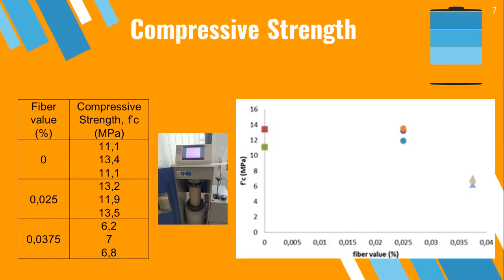For the compressive strength and tensile strength, both also decrease after adding fibers. Looking at the graph of compressive strength, at fiber value 0% we get an average compressive strength of maybe 12 MPa. At fiber value 0.025%, we get an average of maybe 12, similar to the initial compressive strength. And at the final fiber value of 0.0375%, we get a decreased value, maybe an average of 6.5.